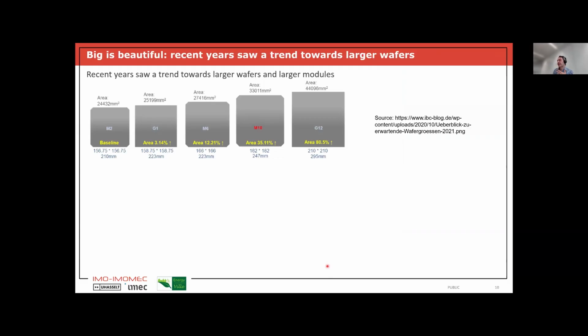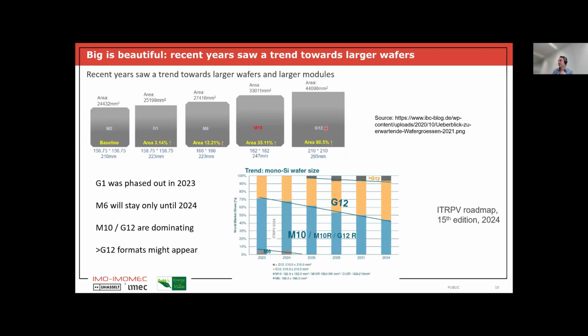So if we now look at some trends of the recent years, today in the industry, everybody is using these very large wafers that are called M10 or G12, that are typically 180 by 180 millimeters or 210 by 210 millimeters. If we go back a couple of years in the history, then for a long time we had a standard size which was much smaller. It was only 156 by 156 millimeter. But today we can make much larger wafers in a very well controlled way. The wafers are very stable, although they are also quite thin. They're only 150 micrometer thin typically. And this actually gives a cost benefit. So everybody is using these large wafers.